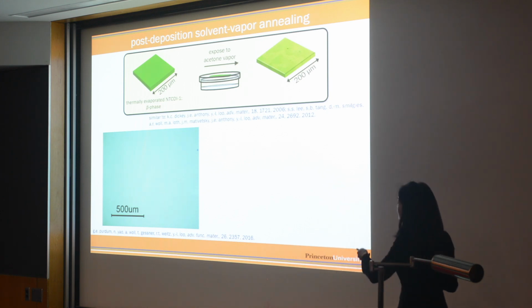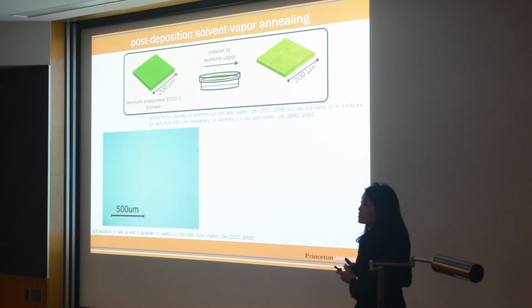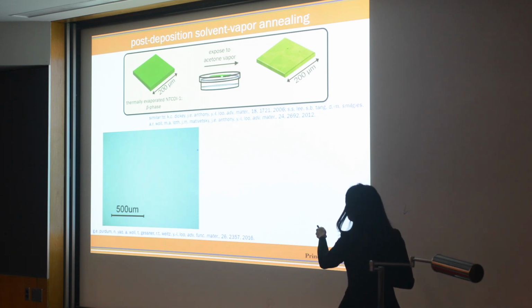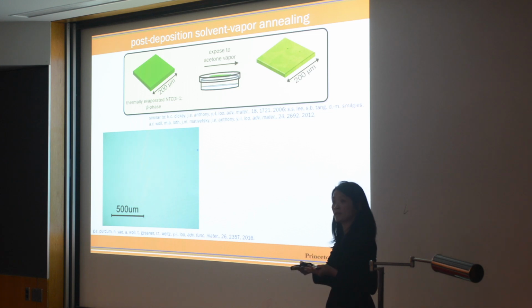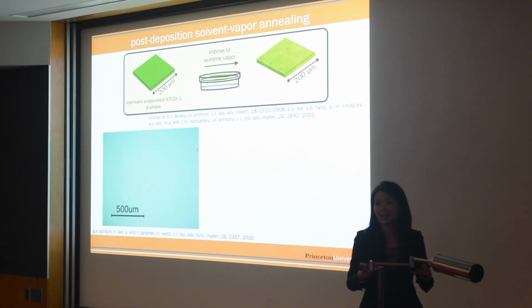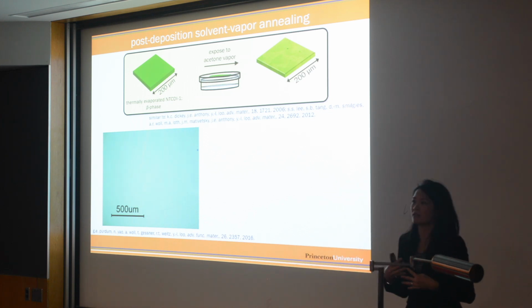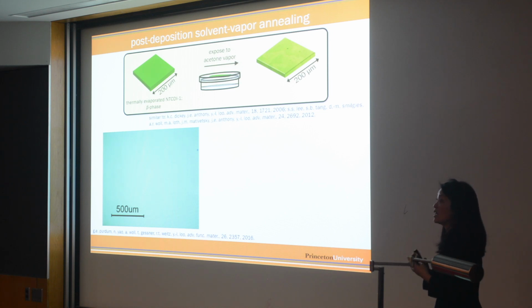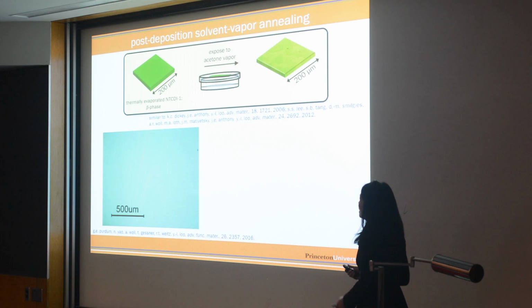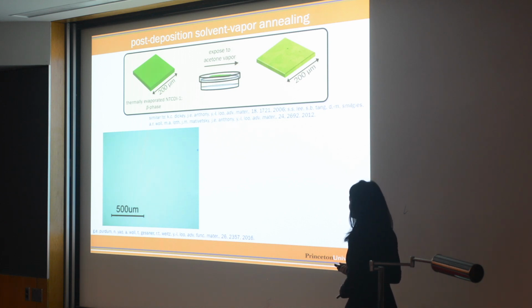And so here, this is the solvent annealing process. We take this film that is already the beta phase, and then we put it on the top of a Petri dish. We expose it to a little bit of solvent at the bottom. It's exposed to the solvent vapor. This solvent vapor plasticizes the film, and it allows for rearrangement to occur if rearrangement needed to take place. And so this is a video of the solvent vapor annealing process.